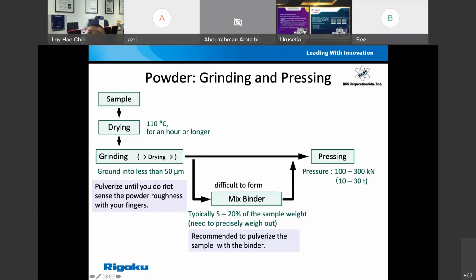But in industry, a lot of times, people control it by sieving. It means after they grind the samples, they pass through a sieve to ensure that all the samples that they collected meet this 50 microns or below grain size. So after you have powder samples dried and ground, the next thing is we can either process with loose powder measurement, but normally we would suggest you go for a pressed pellet. Because by pressing the samples, we can increase the density of the pellets or your samples. It can give you much more accurate results, or you can even detect some light or even some trace elements inside there. It's really the light elements.